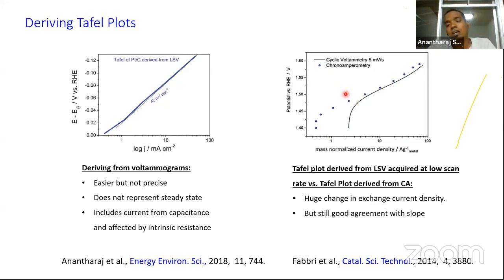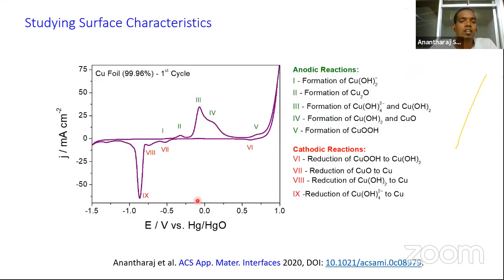So I would suggest you go for chronoamperometry or chronopotentiometry, the steady state techniques, or of course electrochemical impedance spectroscopy. Apart from that, we can also study the surface characteristics of a given electrode material. If you have an electrode material and you don't know the surface composition, I have shown an example of copper foil here. I have chosen a very large potential window, as you can see, minus 1.5 to 1. Within this, there are several peaks, and in the backward scan you can also see several peaks. All these peaks can be assigned to the respective redox reactions, as I have assigned with the help of the standard electrode potential table that we have in the literature. So cyclic voltammetry can be used to study the surface of the material that you wish to study.